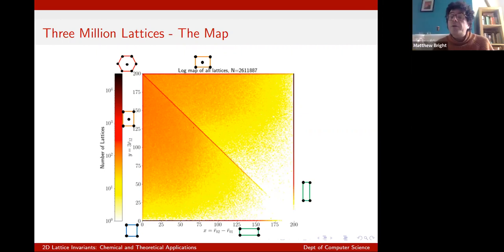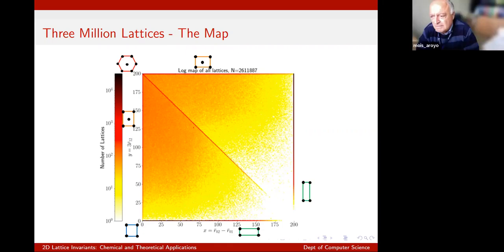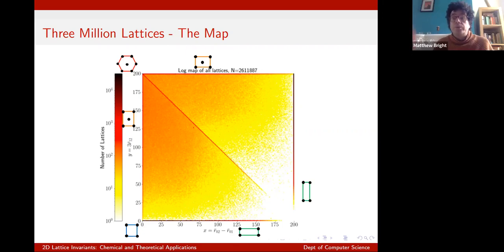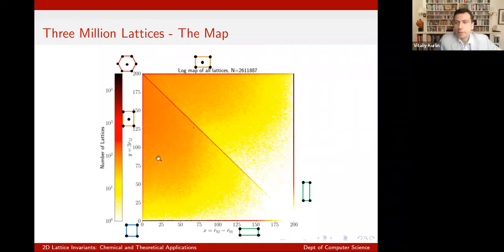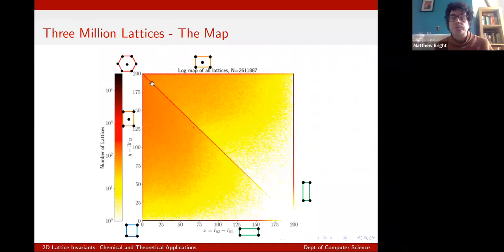We do have some data sets, which are possibly a slightly more physically informative thing, where we've taken just monoclinic lattices and mapped out the one two-dimensional lattice that is not 90 degrees, that is oblique. And you do see a very similar pattern. You see that things want to be close to hexagonal and thin out as you get away from it. You see again these blank spots. Things don't want to be long and thin for fairly obvious physical reasons.